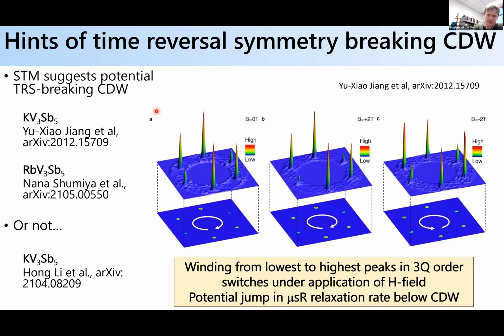And the initial report of this was from Zahid Hasan's group, where what they did was they looked at these 2 by 2 peaks in the Fourier transformed STM data, but then they looked at the 3Q vectors comprising this, and they saw that there is a difference in the intensities when they look at the Fourier spectrum. And they defined a winding going from the lowest to the highest peaks in this distribution of these 3Q peaks. What they found is that they could actually switch the distribution of this intensity by switching a magnetic field. So basically they saw that which Q peaks were favored in the 3Q order was coupled to magnetic field.